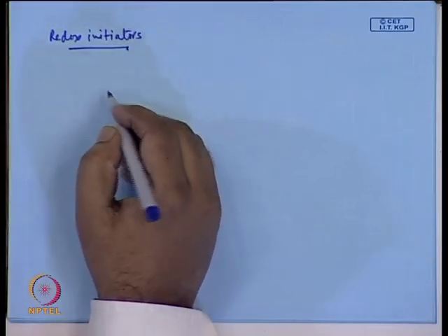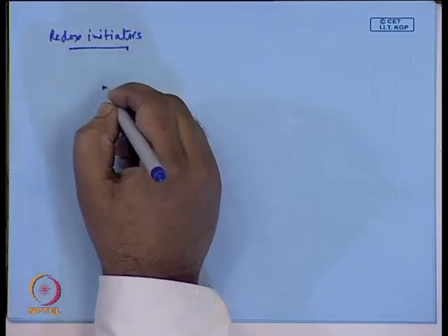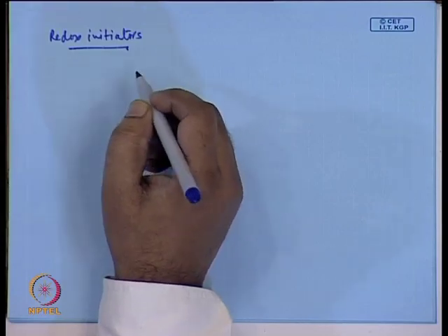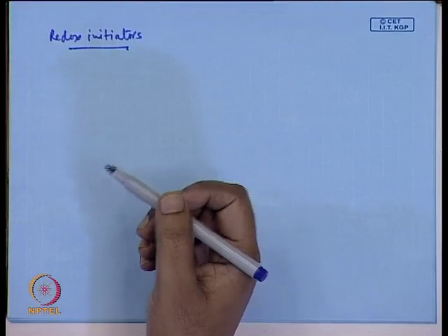We talked about this example of benzoyl peroxide and dimethylaniline in the last class, and we also showed the values of Kd, and we have seen that Kd is much higher for this redox reaction, which means the radical polymerization where the radical is generated by a redox reaction can be done at lower temperature, including a subambient temperature, compared to the thermal initiator.